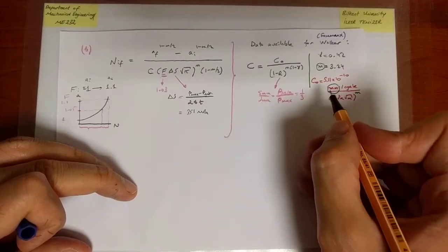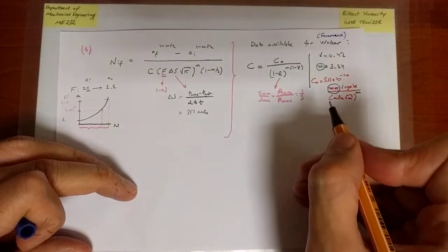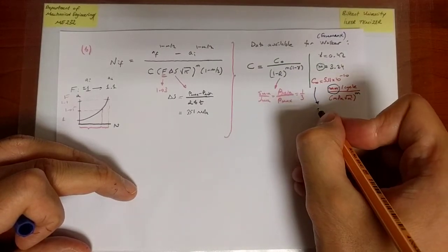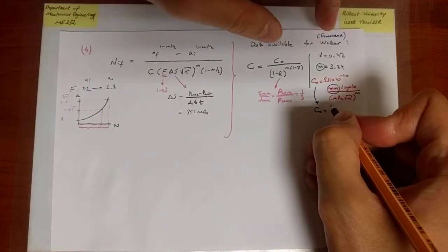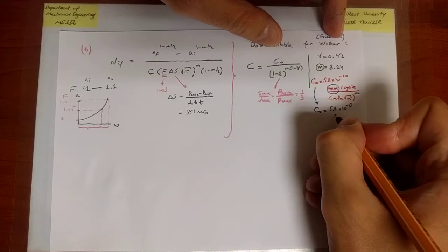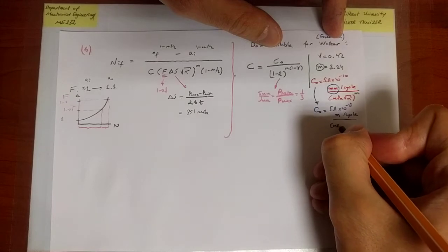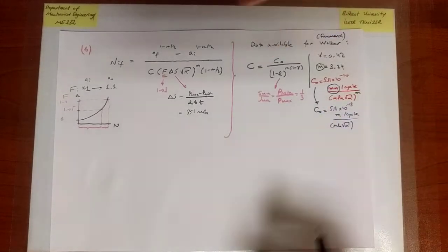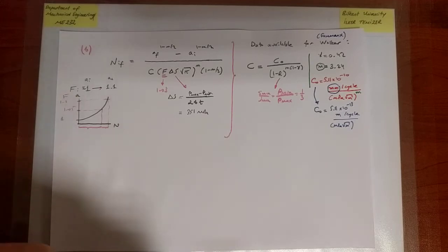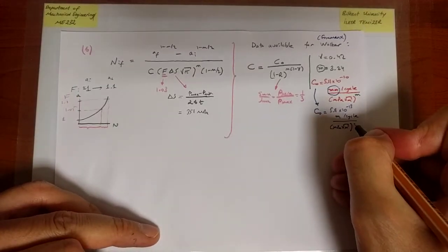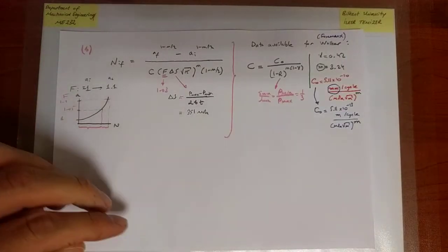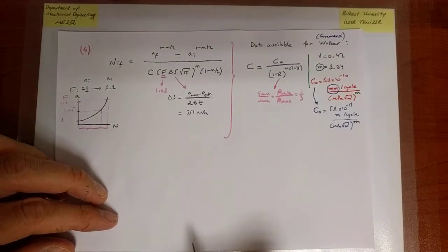So you always have to, in a first step, make sure that you take this value of C naught and convert it, before doing anything else, this is a typical mistake, to meters per cycle, so that everything else that I will be doing will be consistent with the rest of the units. Here I have meters, there I have meters. Eventually everything will work out fine. That m is 3.24. Okay, all right, so that I've done.